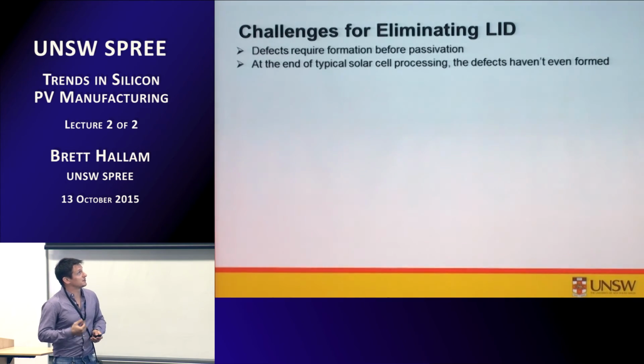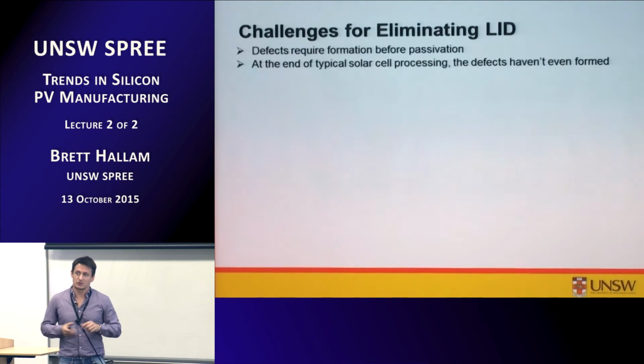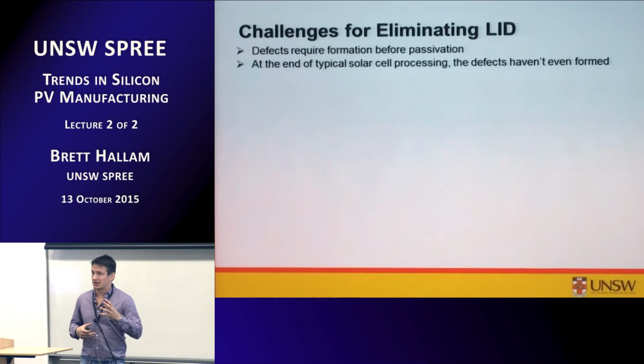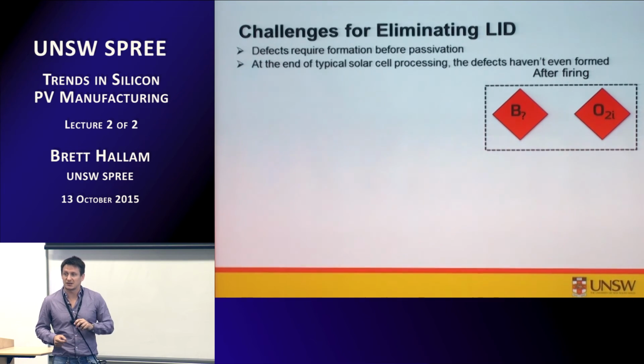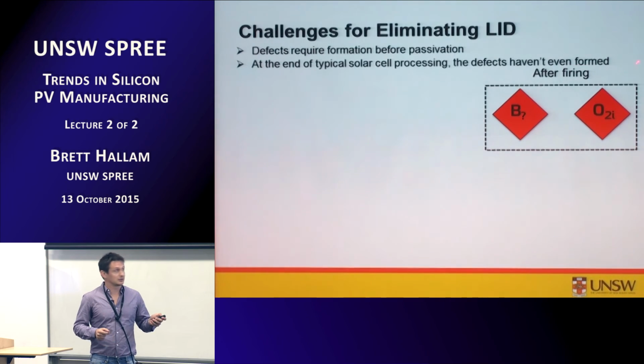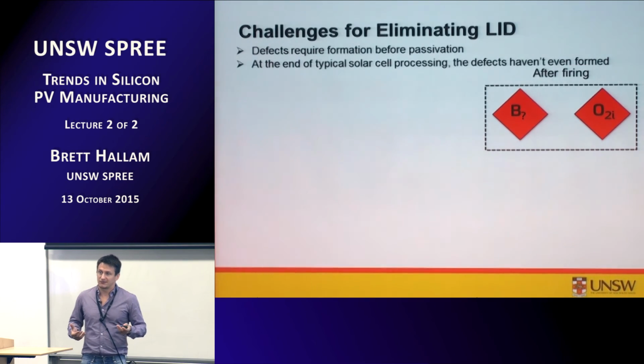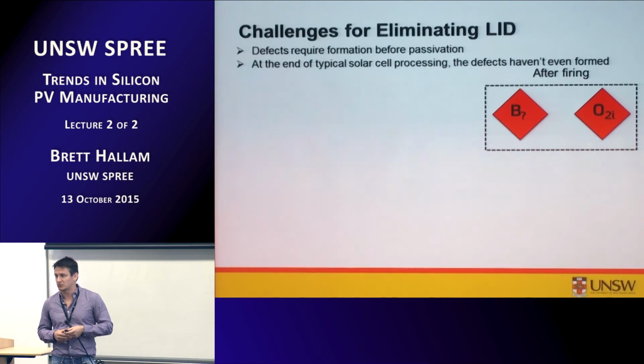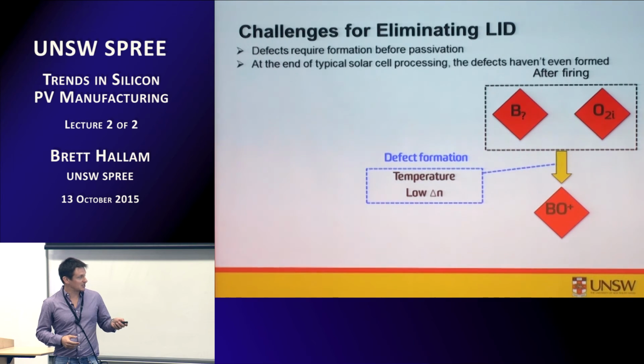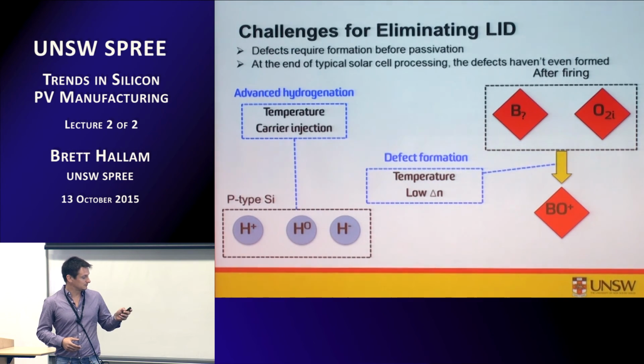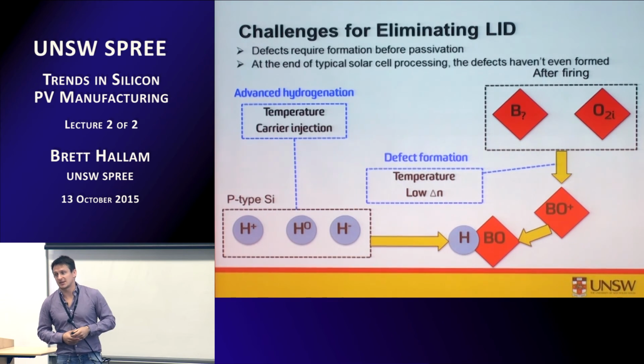So in terms of the challenges for eliminating LID, a lot of the defects we typically deal with in the solar cell are inherently in the solar cell already, like the structural defects, the grain boundaries, the dislocation clusters. They're always available in the solar cell, so we can attempt to heal them through gettering, passivation, thermal-based processes, etc. One of the problems, particularly for these carrier-induced defects, is we take a finished solar cell, so after firing, we haven't actually formed the defect yet. And from our understanding, we can't passivate a defect that hasn't formed yet. So first of all, you need this defect formation process, typically this temperature and carrier injection. Then we can bring a species in to passivate it, etc. And then we have our stable process.